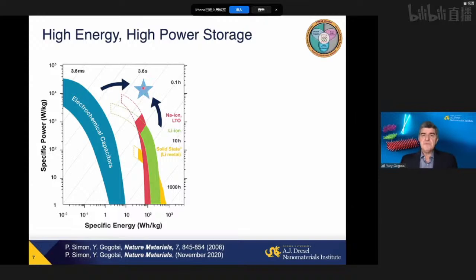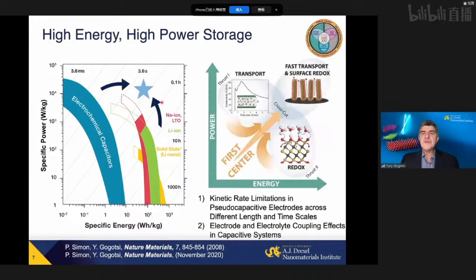Moreover, what does it mean charging batteries quickly? It means that you need to run a high current through this battery. So you need materials which will have high electronic conductivity. Remember that even activated carbon used in electrochemical capacitors has conductivity in, say, tens, maybe 100 millisiemens per centimeter. Actually, very moderate. Graphene and nanotubes go above; reduced graphene oxide, 2000 siemens per centimeter. MXenes can give you 10 times more, being real metals, having high density of states at the Fermi level.